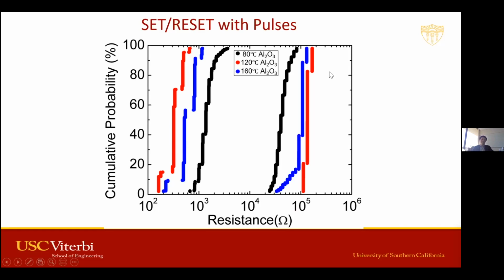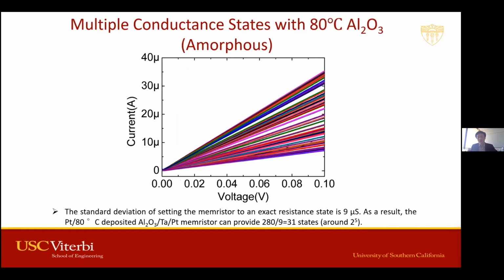What that means is, if you want to build a memory device, you want to deposit your switching layer at the highest temperature that still keeps the switching layer amorphous. In this way, the device has a larger on-off ratio and performs more consistently as a memory when you switch it on and off with pulses. But of course, we are more interested in using those devices to implement a small brain for the simplest robot.